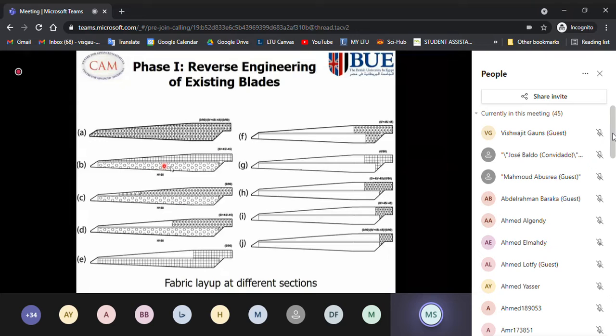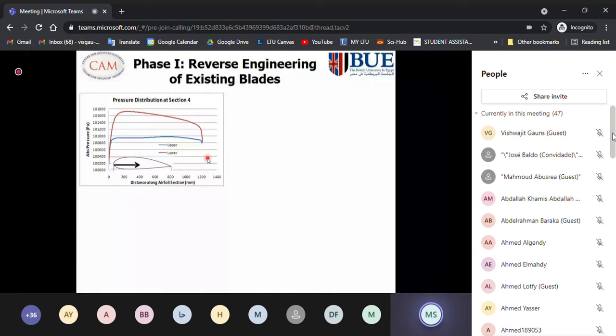This area here where we have these hexagonal shapes, this is where we have the foam. So you start with 1 layer, or I think this is like 3 layers of fabric, and then you put 1 layer, and then the rest is foam, and then another layer. But as you can see, we decrease the length of the fabric, and then we cover the foam with another layer, and then we continue to build the thickness close to the root, where the blade will be fixed. And at the same time, the group working on the aerodynamics developed the pressure distribution at different sections, and they give it to us to implement on the structure of the blade.